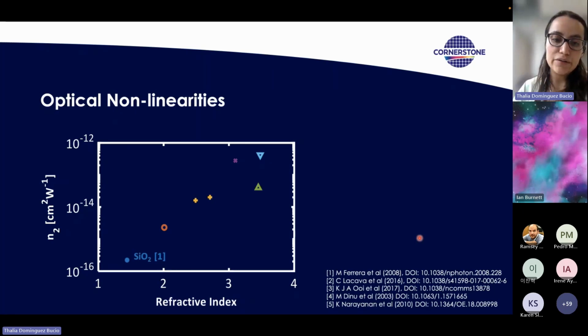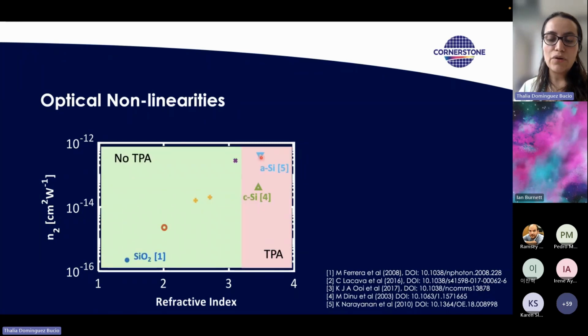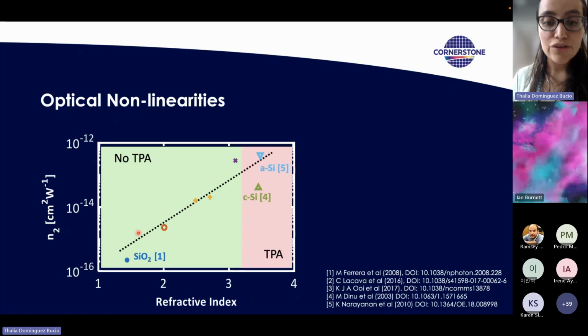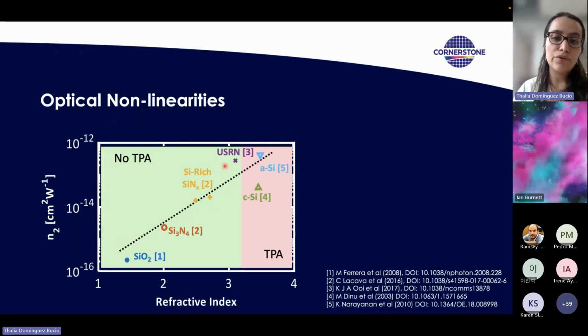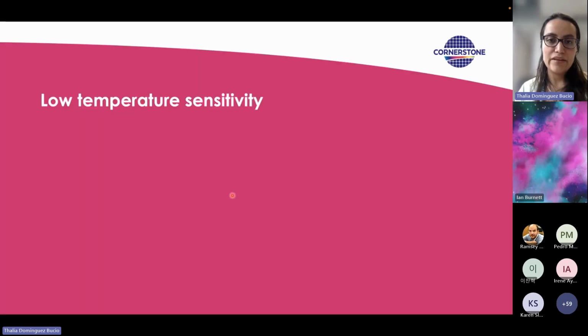If we look at this plot, in which we have the refractive index against the nonlinear coefficient, we can see that we have the silicon dioxide here, in the lower part of the spectrum, and then we have the amorphous silicon and the crystalline silicon, which have a higher nonlinearity. In this case, when we have the silicon layers, we have two photon absorption, and in the lower part of the spectrum, we have no two photon absorption. This is important because if we start increasing the silicon content in our silicon nitride layers, we can start seeing a higher nonlinear coefficient, which might give a more efficient process, all the way to the point that we get ultra silicon-rich nitride layers with a refractive index of 3, which makes them very useful for all optical processing applications.